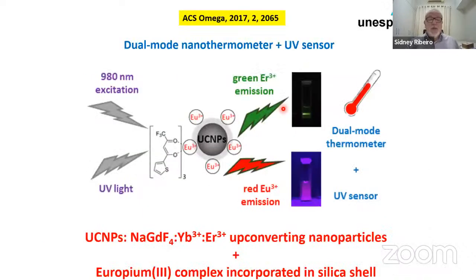So coming back to the work made by Karina, we have the upconversion nanoparticles, and we coat these upconversion nanoparticles with silica, porous silica, obtained by Sol-Gel. So we incorporate europium ions in the porous silica, and we fabricate in situ this complex of europium. It means that this particle, when you shine in the infrared at 980, the upconversion nanoparticles will emit visible light in the green and the red. And when you shine in the UV, you will excite the europium complexes on the silica coating, and you see the red emission from that.